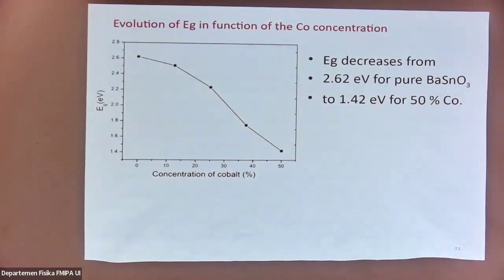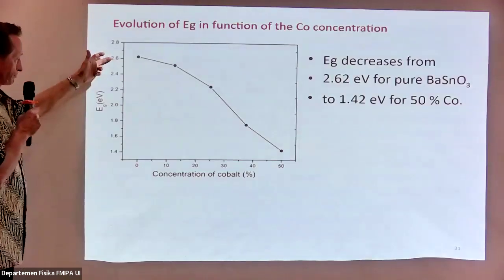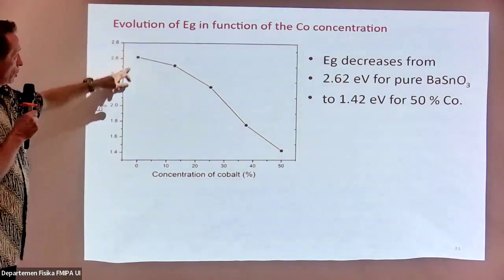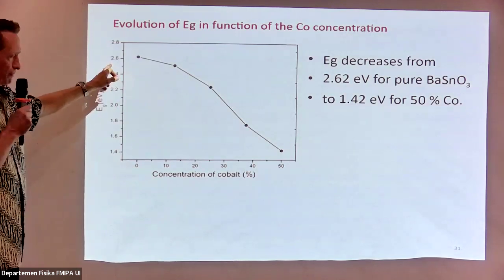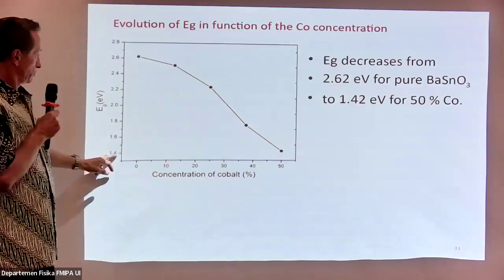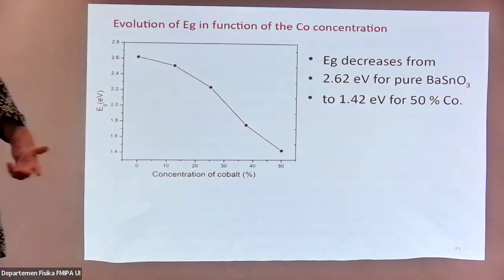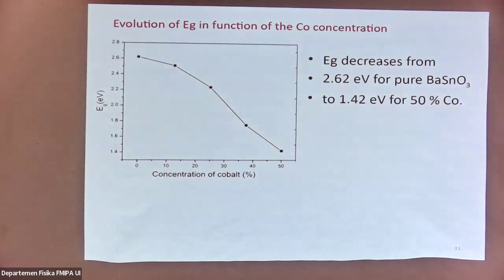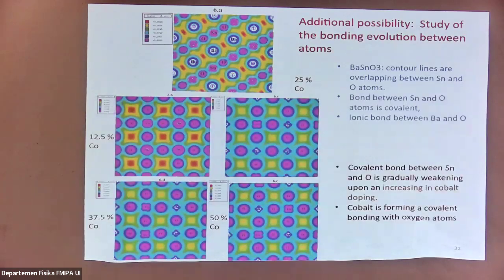And here's the result. We plot the evolution of the gap: without doping, 2.6 electron volts. With 50%, we decreased to 1.4. So that wasn't bad because that was a large decrease of the gap. That's what we performed. And we go to the next step, which was the experimental applications. But before that, of course, I show you some extended applications you can do with DFT tools.